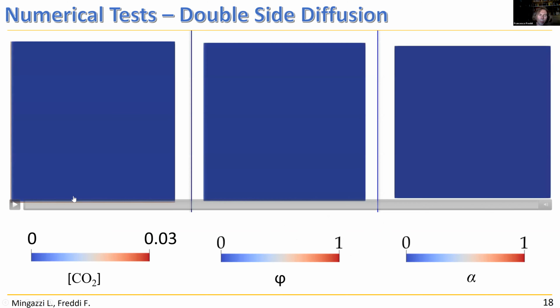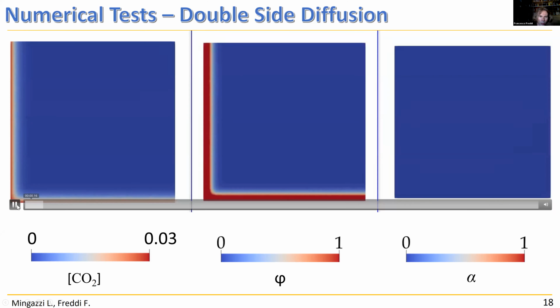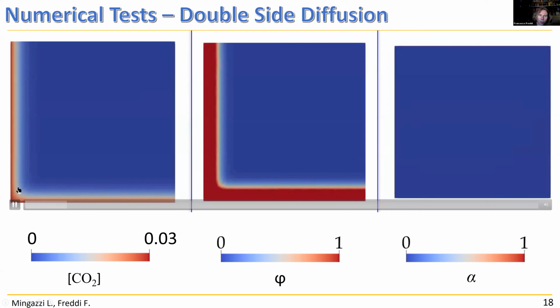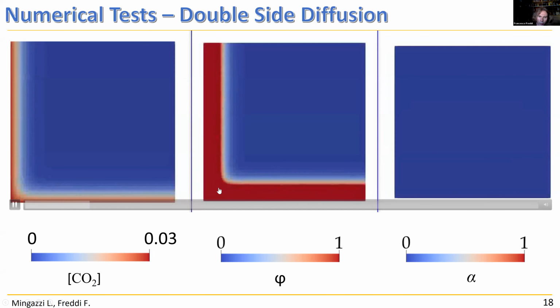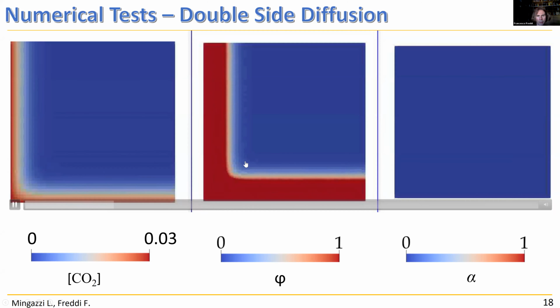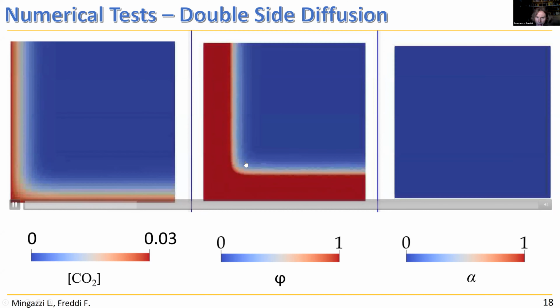And here I'm reporting the numerical results in terms of CO2 concentration, the carbonation front position, and the damage state. So you can see that CO2 diffuses within the solid. There is a carbonation front that penetrates within the concrete element.